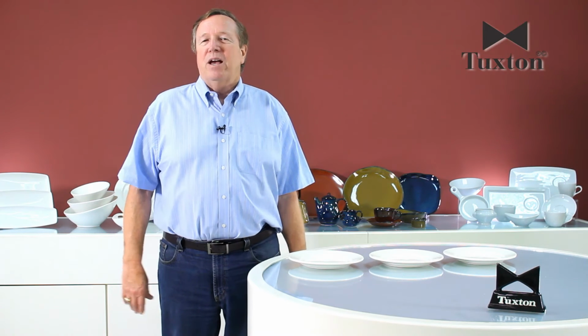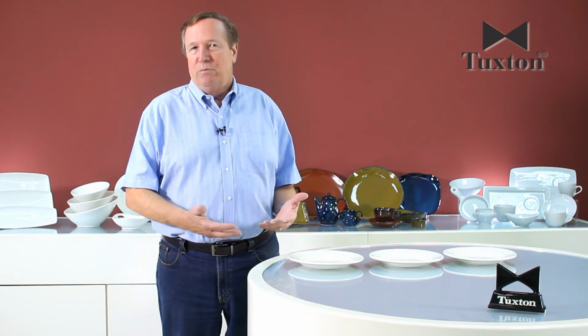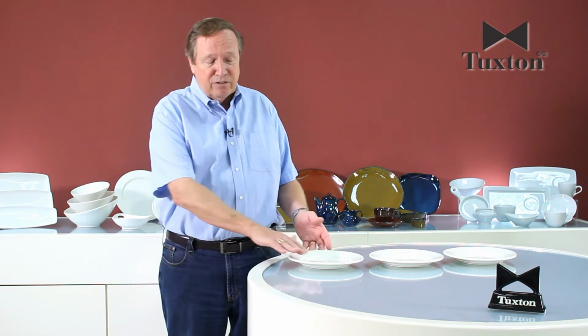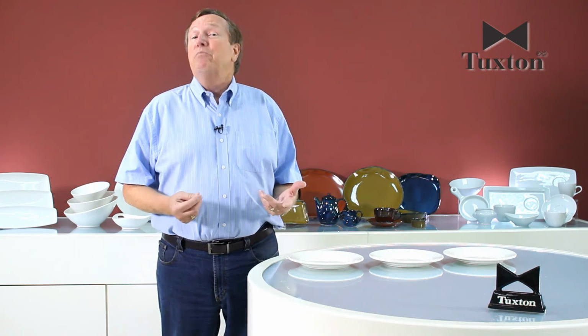There's a popular misconception in the industry that a glazed foot will not scratch or mar another piece of china, which in fact is not true. It's just the opposite. An unglazed or polished foot will not scratch as much. And the reason for that is glaze is, like we talked about in another video, basically a glass, and if you look at it under a microscope, you'll see that it's crystalline in structure, and even though the glaze feels very smooth, it's very abrasive.